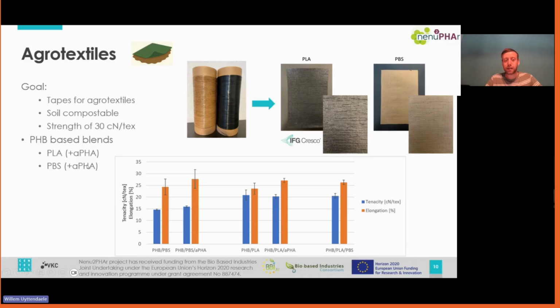And what we saw there is that with blends of PHB with PLA or PBS, we could get quite close to the strength requirements for these agro-textiles. And this was then done in cooperation with IFG Cresco.